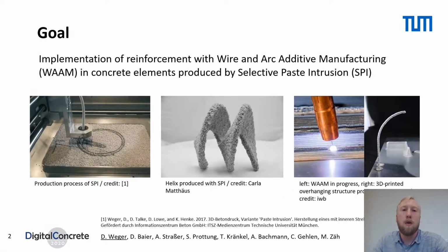This paper presents first results of an ongoing research project with the goal of implementing reinforcement with wire and arc additive manufacturing in concrete elements produced by the selective paste intrusion method. On the left side, you can see a scene of the selective paste intrusion production process where the nozzle applies the cement paste to bind a layer of aggregates in the particle bed, and the advantages of SPI structures are the high compressive strength with over 78 megapascal after 7 days and the high durability.